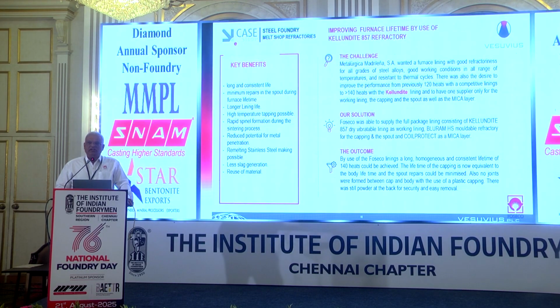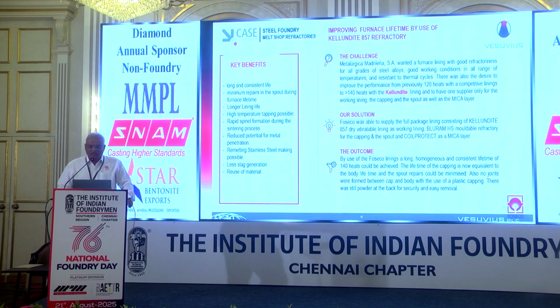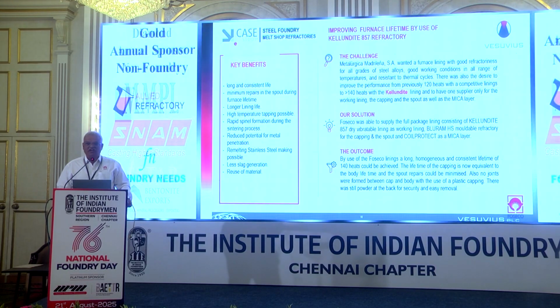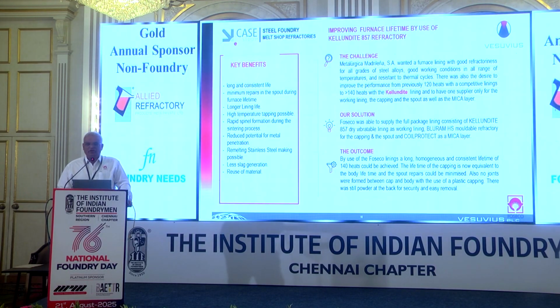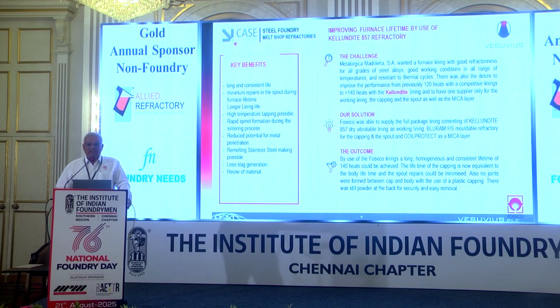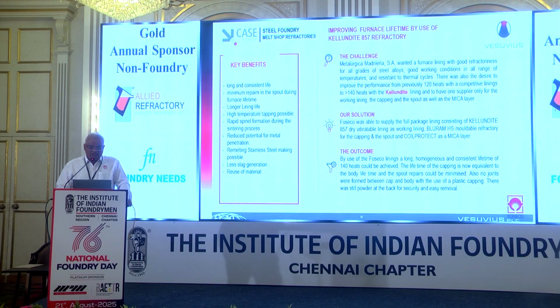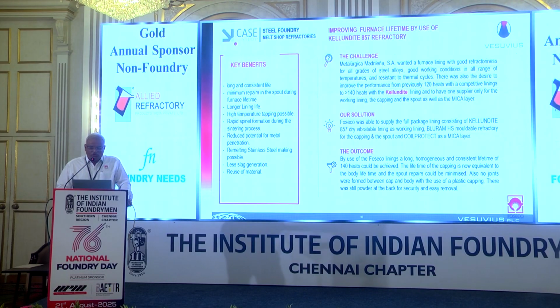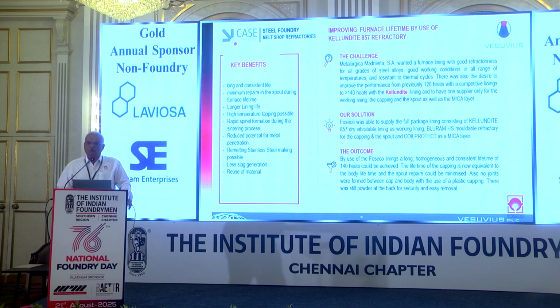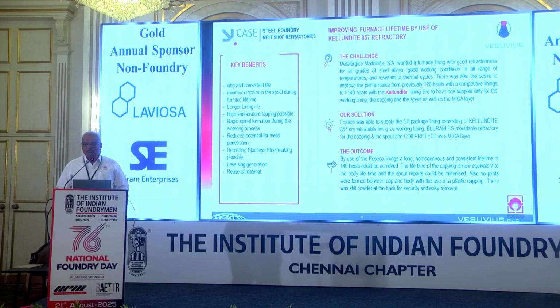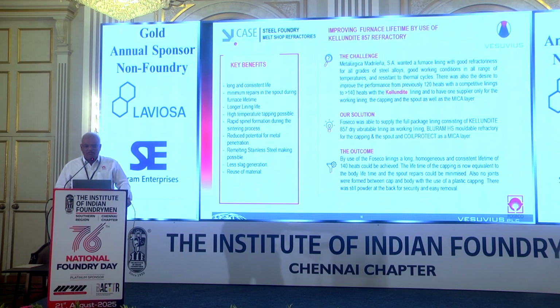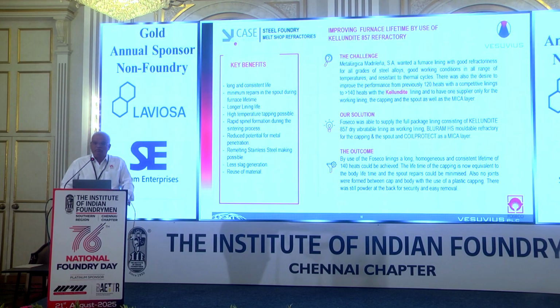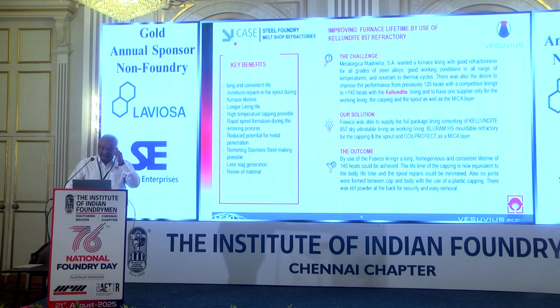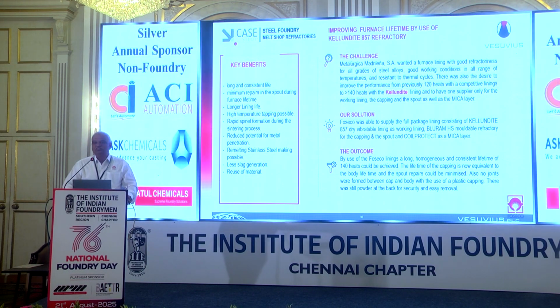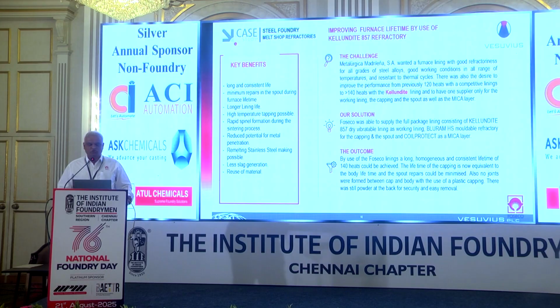So with this they achieved an average life of 140 heats. Earlier their average life was 120 heats. So average life is increased, and they got all the products together from one supplier, and whatever their requirements, the mold cracks at spouts and all these things, repairs, are also reduced.